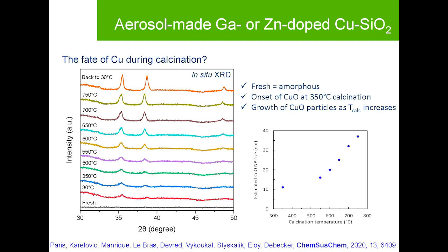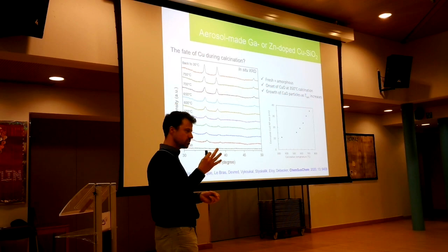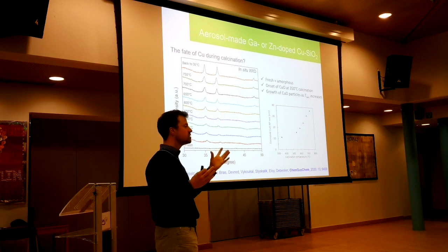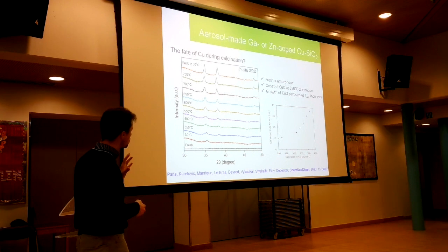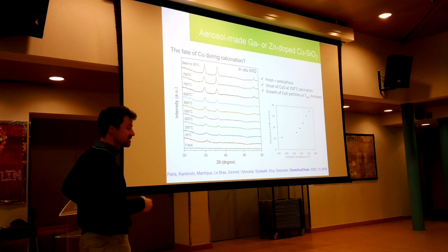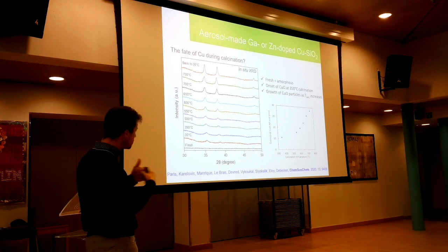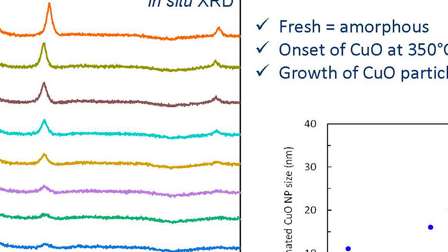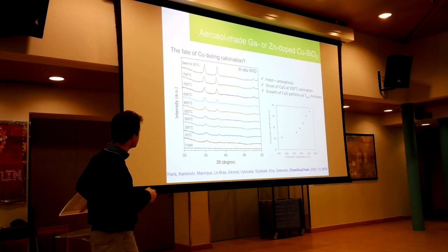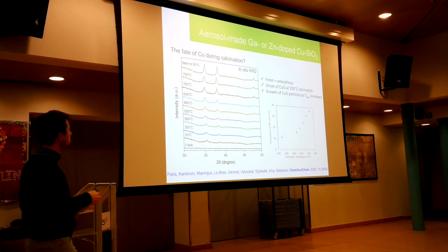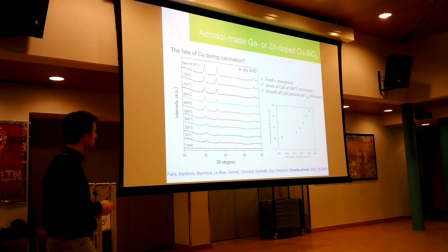Okay, in spray, in aerosol, we spray those small droplets and they are dried in 1 second or 2 seconds, so it's very fast. What we get at first is something that is completely amorphous. It's just silica with copper in it, right? But then when we calcine to remove the surfactant, to release the pores, what we see is the appearance of copper oxide, right? That's the calcination temperature that is done in situ in the XRD apparatus. And we see those peaks of copper oxide coming in, right? Coming out and getting bigger and bigger.